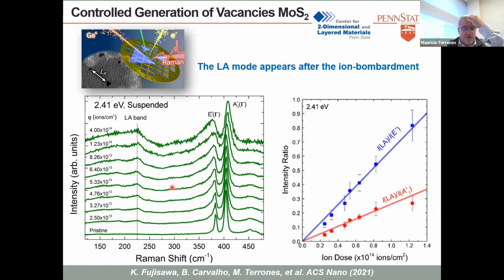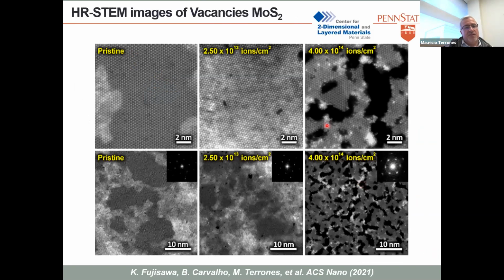I mean, it's a different concept, but you can associate that to the defect. And again, this is what happens. So you can then plot the intensity ratio of the LA mode with the E prime or the A1 prime, as a function of the dose, right? And these are sort of linear behavior. So one of the things is that this is a pristine system.